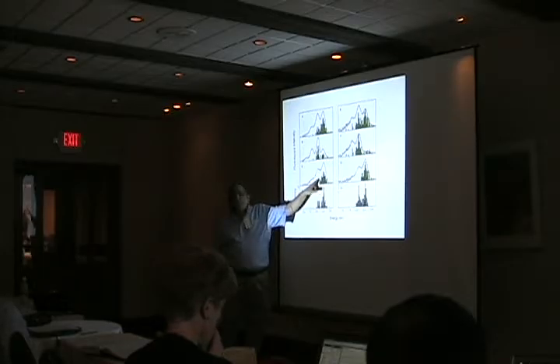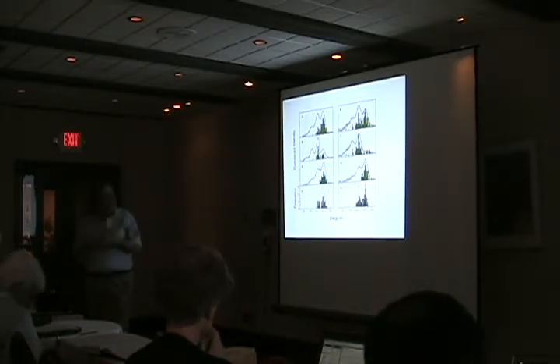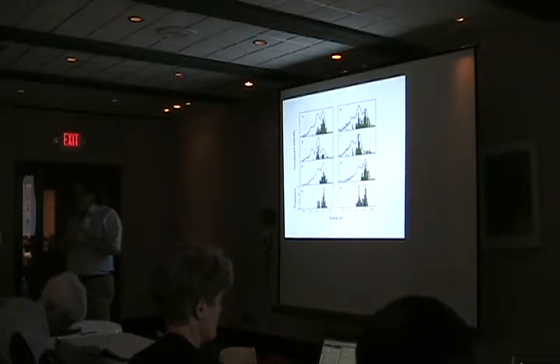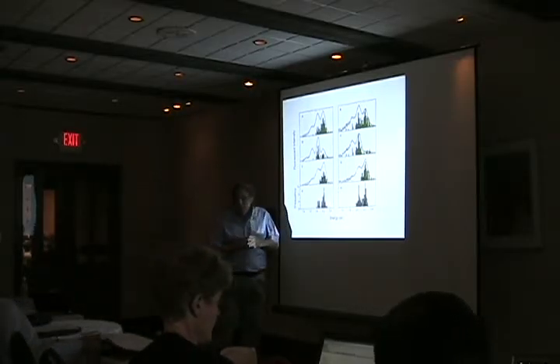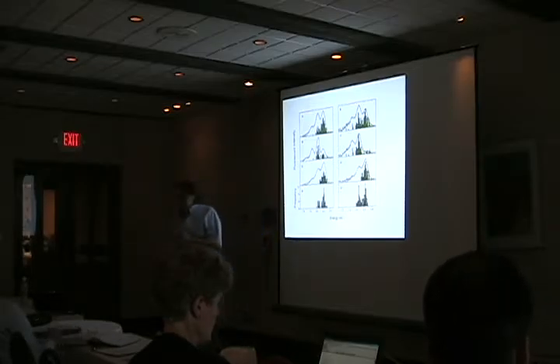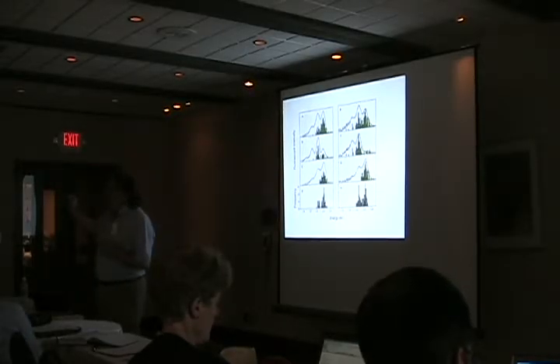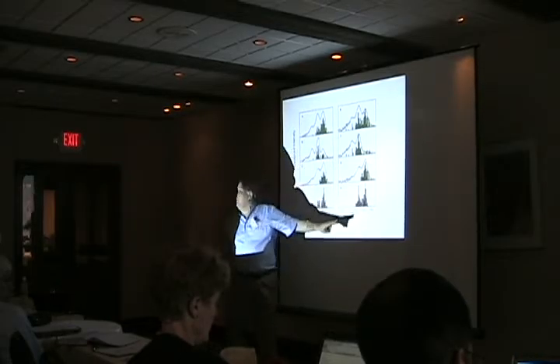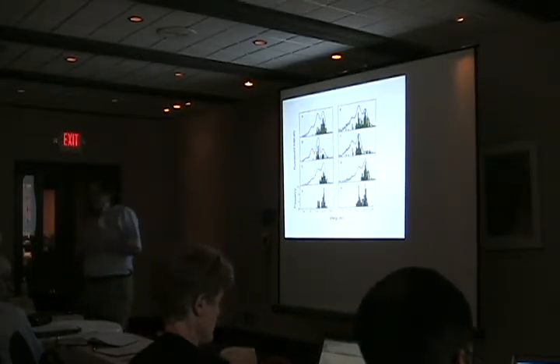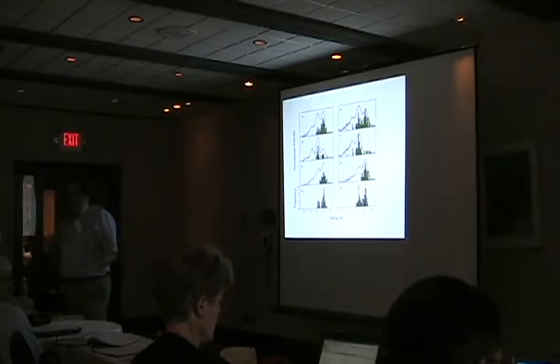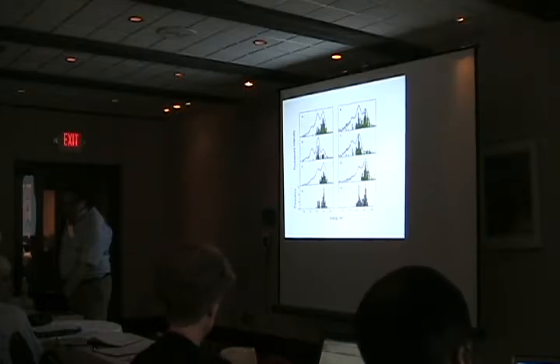And I'll just quickly mention this. These individual stick structures here are taking an ensemble of molecules at very low temperature, where the spectra are extremely sharp, and building up the ensemble in much more detail. And you really see the intermediate states in energy transfer. What's really fascinating, and fascinated people tremendously about this area, is two things. One, that in many cases a single polymer chain involving as many as 30 or 50 chromophores, if you will, sites where the energy would be stable, emits perfectly from the lowest energy site. Two, that there is this bimodal distribution, which is our sort of claim to fame, resulting from the morphological effect on the exciton energy. Why are there two sites and what is going on there?